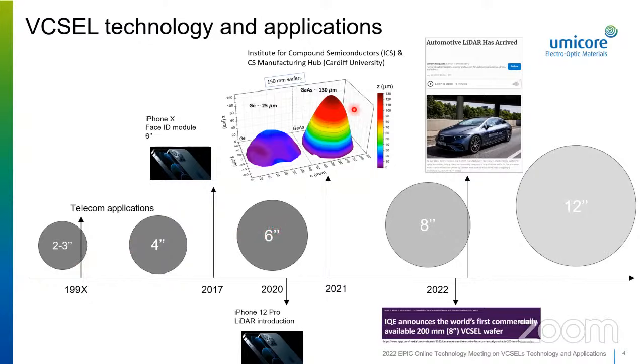This is a very nice slide from Cardiff University, where they observed the bow of 150 millimeter wafers and compared a germanium wafer and a gallium arsenide wafer. What is happening is that you have your DBR stack, and the DBR stack consists not only of gallium arsenide, of course, but also of aluminum arsenide. There you have a little lattice mismatch, and because of that, stress builds up and your wafer starts to bow. These problems are of course solved in current production, which adds certain cost.